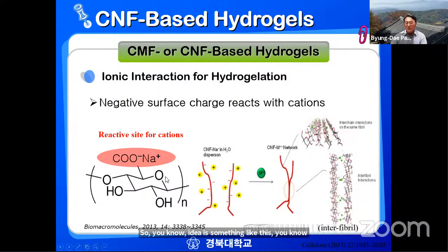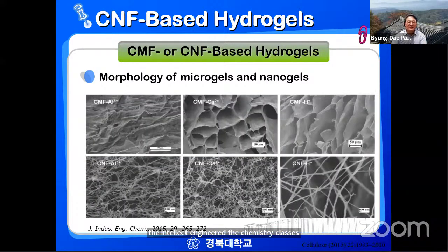So the idea is something like this. When you do a TEMPO oxidation, you have sodium carboxylate groups on the surface, which are negatively charged, and then you add the positive metal cations, and then they have an ionic interaction between the sodium carboxylate and the metallic cations, and then you get interfibrillar reactions, and then you make the hydrogel. You may try this; it is very simple, so you can try it in the lab in your chemistry class as well, maybe. Okay, and then we look at the morphology of these hydrogels, with the aluminum cation, calcium, and the protons, and the different morphologies at different magnifications. This is a much tighter morphology with the cations, but the protons give very loose structures.